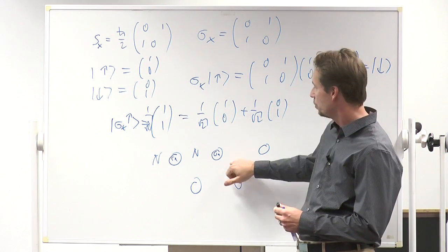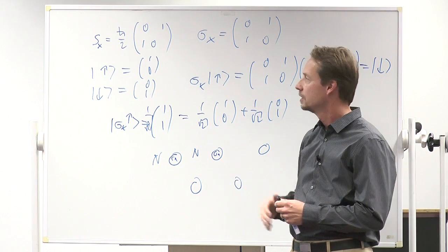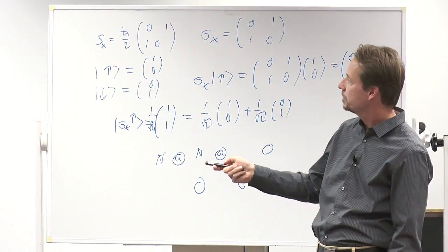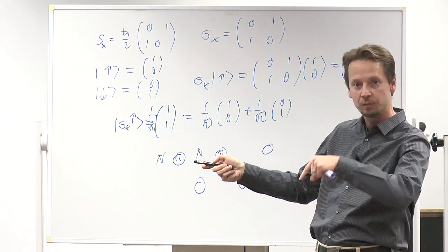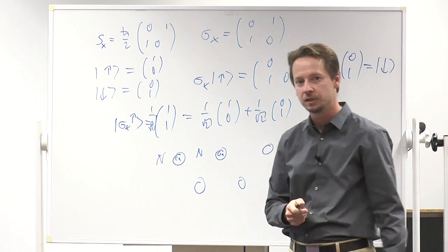Right? This we only know from calculations, density functional theory calculations, to be precise. But the measurement of the height, we can do that directly here. So it's about 30 times less current if you keep the same height over the copper nitride than on the bare metal.